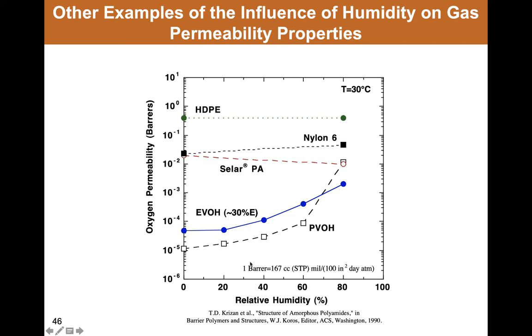One of the drawbacks of using ethylene vinyl alcohol and polyvinyl alcohol is that it's very sensitive to moisture. As you might imagine, polyvinyl alcohol itself would be soluble in water. And so when it's exposed to water, even at low levels of humidity, the polyvinyl alcohol will absorb a lot of water, so much so that it swells extensively, and there's an increase in polymer chain motion, an increase in free volume, and then there go the diffusion and permeability properties.